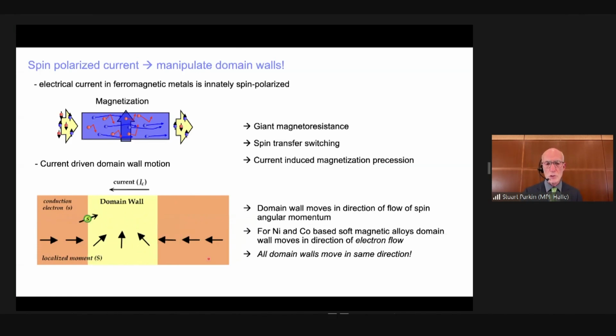In between, you have what is called a magnetic domain wall, where the magnetization switches from one direction to the other. And on the nanoscopic scale, this domain wall looks like an entity. It looks like a particle with mass and momentum. But now, if we introduce current into this system with magnetic domain walls, the current, you can see as the moving electron with spin, will, as it crosses the domain wall, adiabatically transfer its spin angular momentum to the fixed magnetic moments in the domain wall, causing them to rotate and the domain wall to move if sufficient numbers of electrons and their spin angular momentum are transferred into the domain wall. Now, it turns out this is a very efficient process.